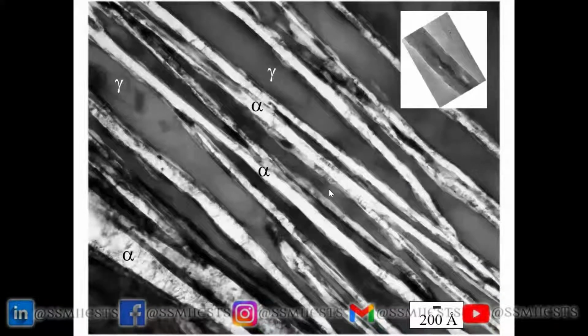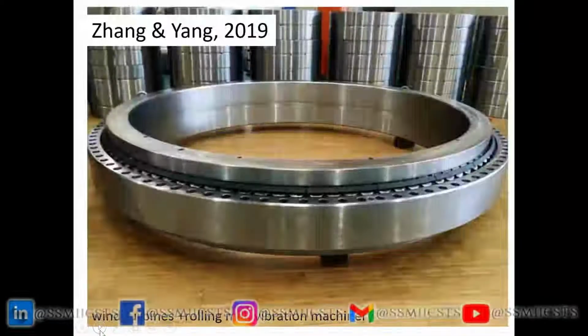The next slide shows a component that is made using this structure, this nanostructure. So this is a very large bearing. Okay. So for wind turbines, you have a 4-meter diameter bearing. The rolling elements in this bearing are made from the bulk nanostructured steel. The ring is too large at the moment with the facilities available to make from this nanostructured bainite, but in the background you can see smaller bearings. And I'm told that one of those bearings has a ring which is made from nanostructured bainite.